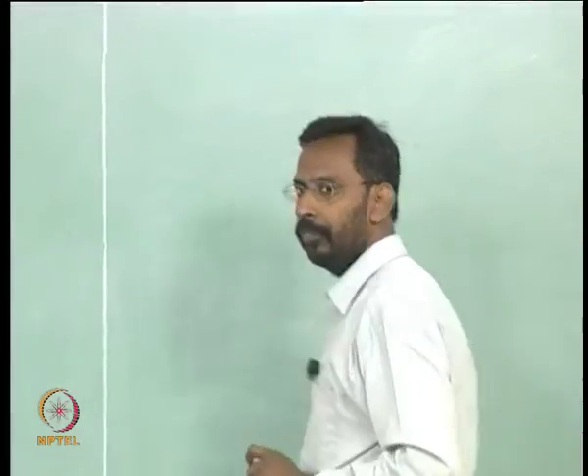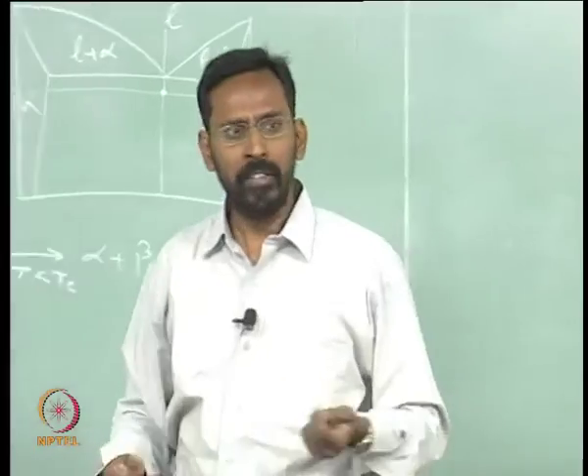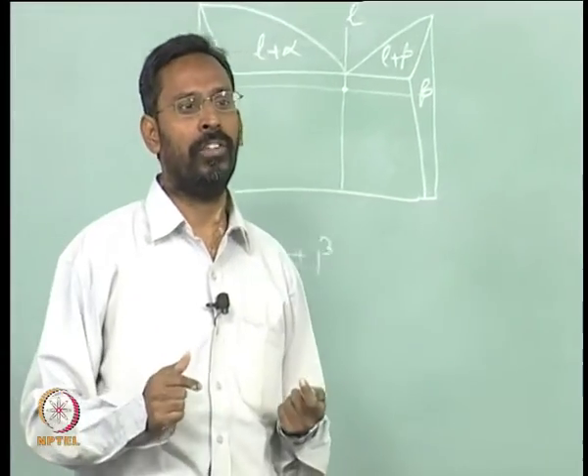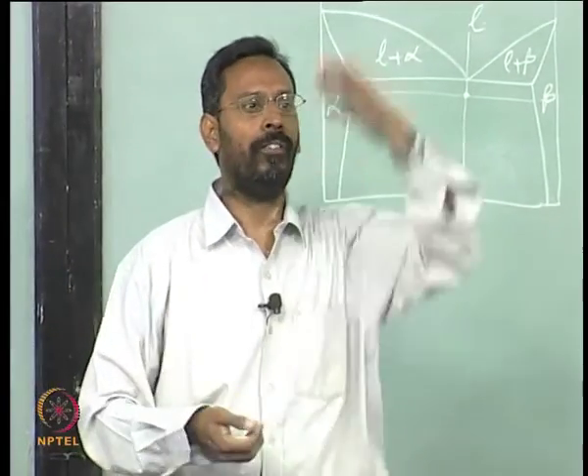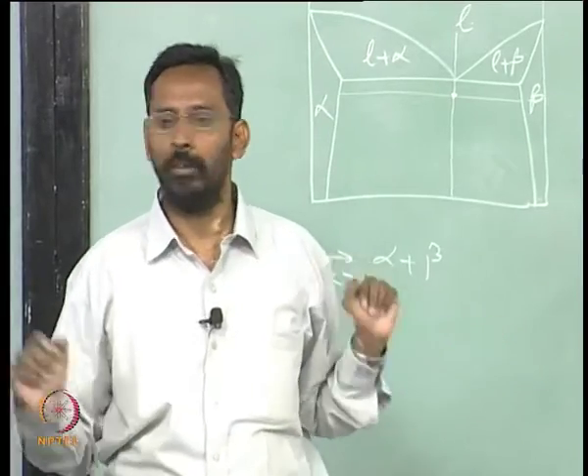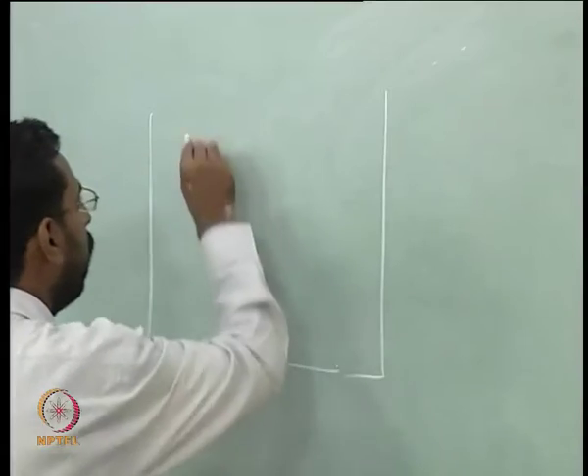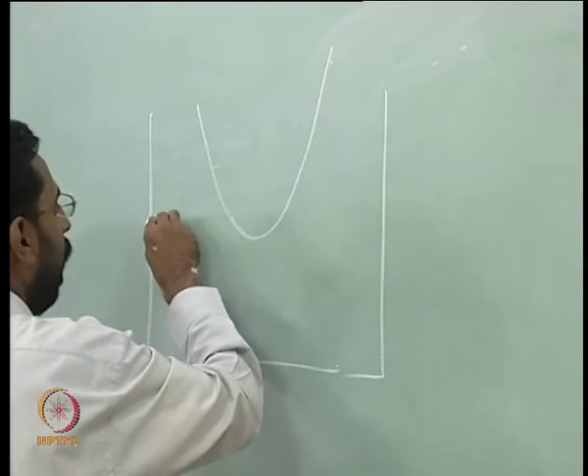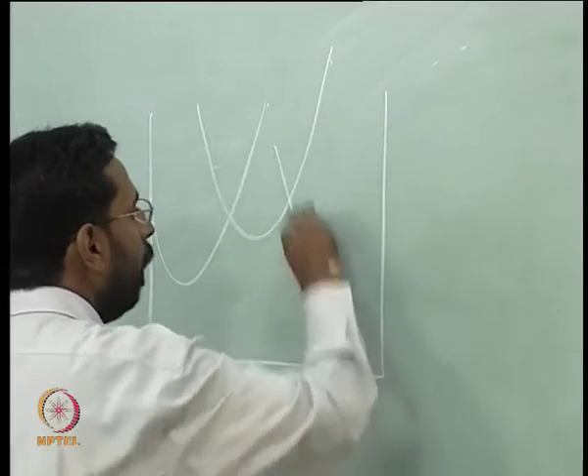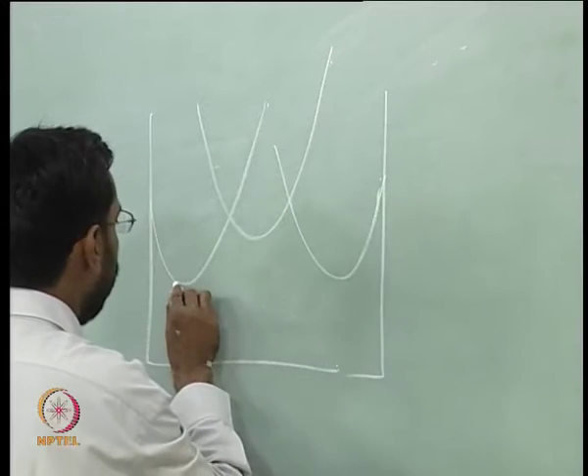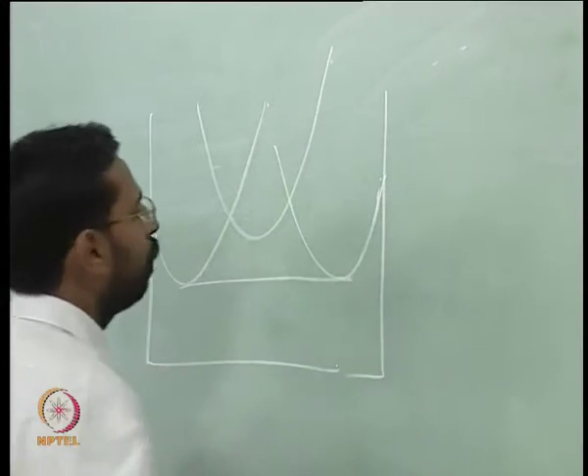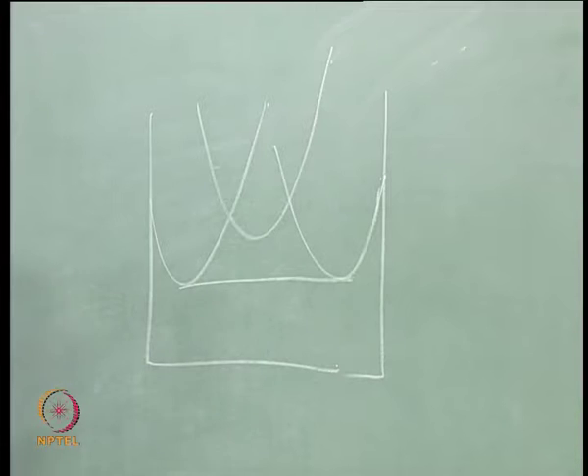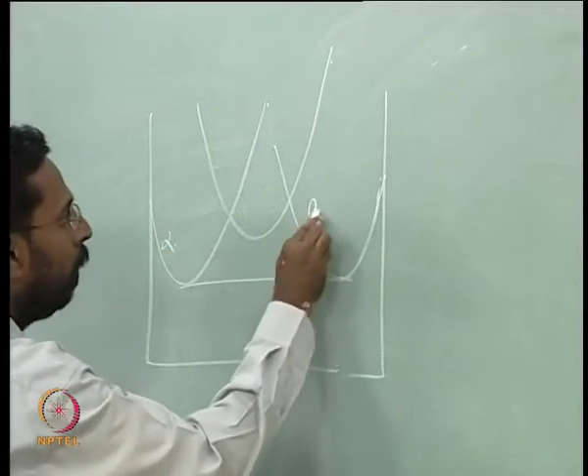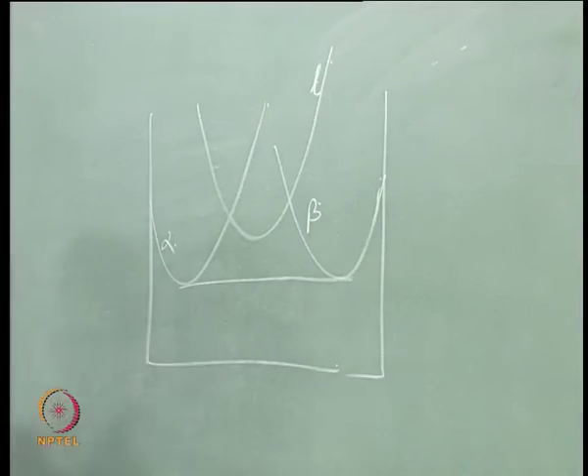What is stable at that temperature? Can you tell me? Alpha plus beta. That means the alpha and beta free energy curves should be below that of the liquid. By now this should all be clear to you. So if that is the case, I can easily draw a liquid curve, an alpha curve, and a beta curve, and draw a common tangent between them. So this is the alpha curve, this is the beta curve, this is the liquid curve. Clear.